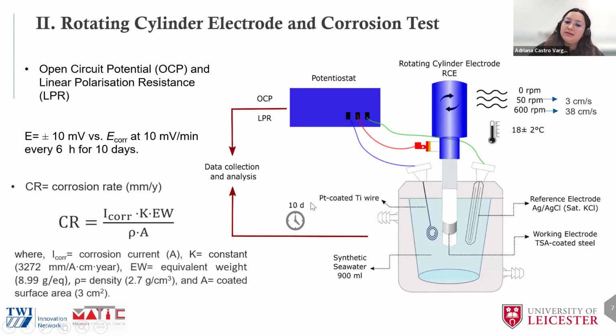After 10 days of exposure of these coatings, we collect information and analyze it. Basically, we monitor the open circuit potential and the linear polarization resistance. The scans were obtained at 10 millivolts per minute, polarizing at plus minus 10 millivolts regarding the corrosion potential every 6 hours for 10 days. And the corrosion rate was calculated following this equation, using the current density that we obtain from LPR.